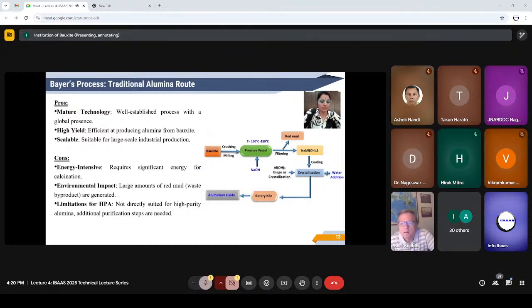So what happens in this process? As we know, first bauxite is crushed and ground to a fine powder. Then it is mixed with a hot concentrated solution of sodium hydroxide, which causes the alumina in the bauxite to dissolve, forming sodium aluminate. The impurities such as iron oxides are left behind as a residue, which is commonly known as red mud.